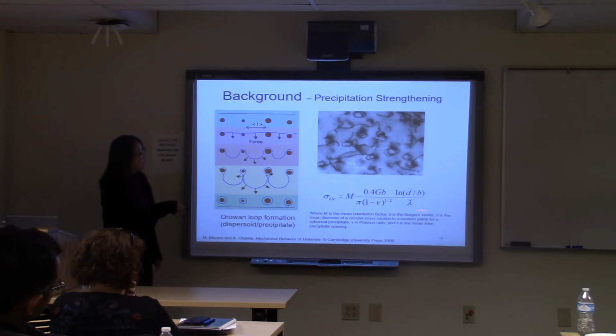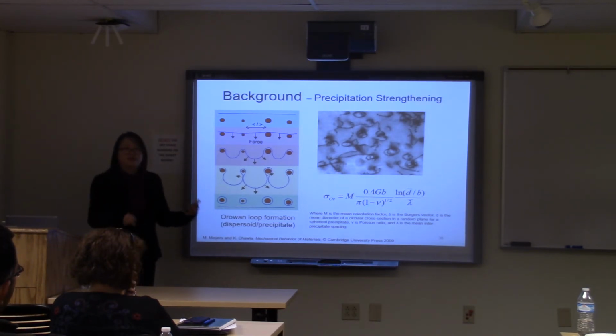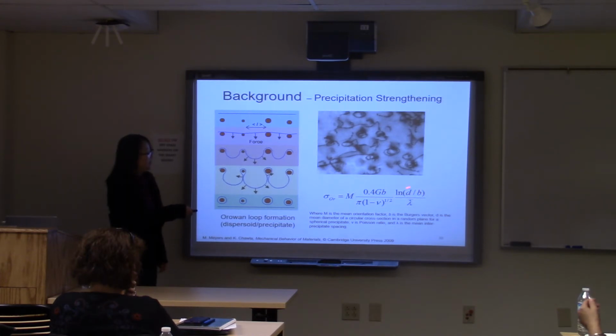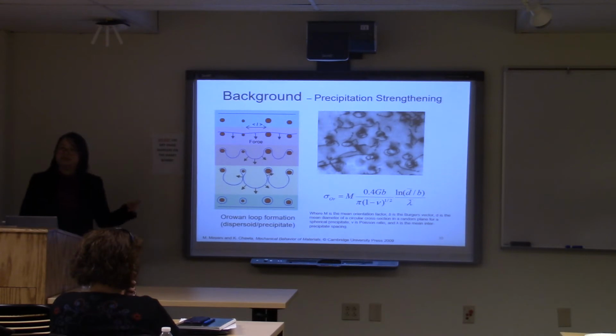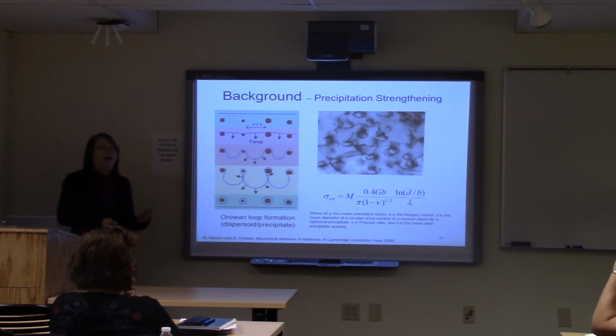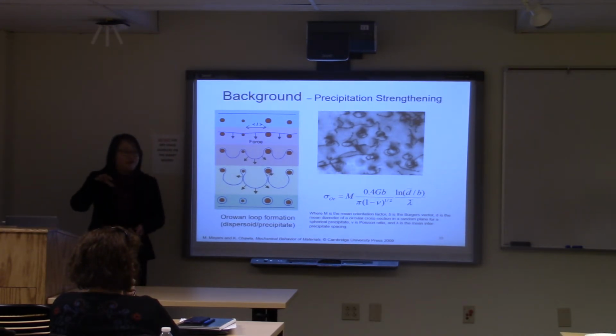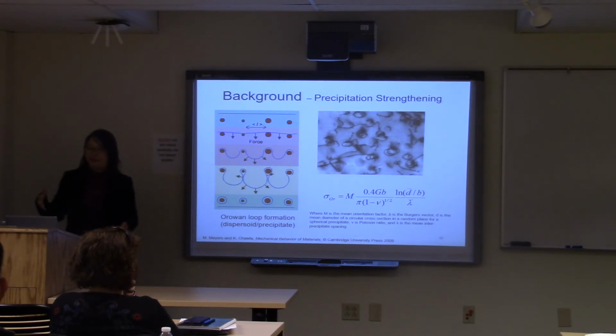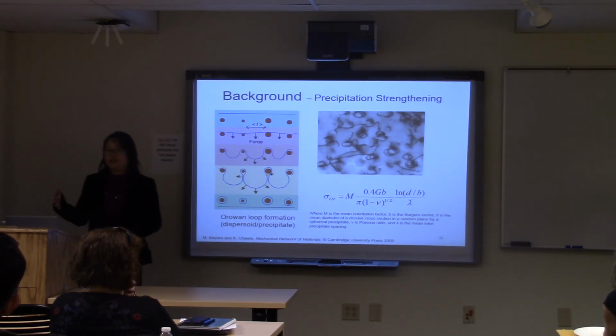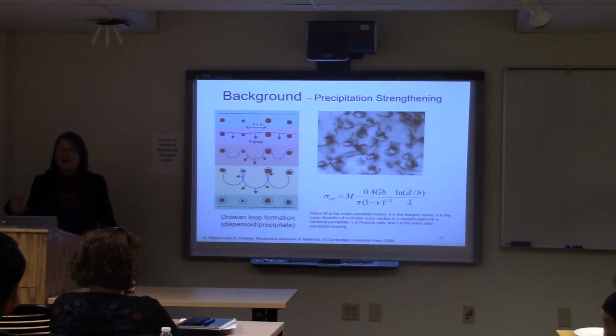And if you look at the equation here, the strength those precipitates can contribute to the material is dependent on the size of the precipitates and the interparticle spacing between them. So that's why the distribution of those precipitates, how you manipulate those microstructures, is important during processing, which can give you the desired property, either higher strength or higher stress corrosion resistance.